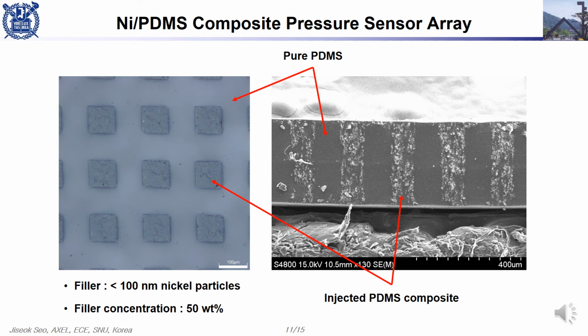Finally, here is the PDMS composite pressure sensor arrays that PDMS composite was injected into the hole arrays that you saw at the previous slide. The filler is nickel nanoparticles with size of 100 nanometer and concentration of filler is 50 weight percent. As you can see at the right SEM image, each cell of pressure sensor is completely separated by the pure PDMS grid. So the possibilities of crosstalk between neighbor cells can be completely eliminated.